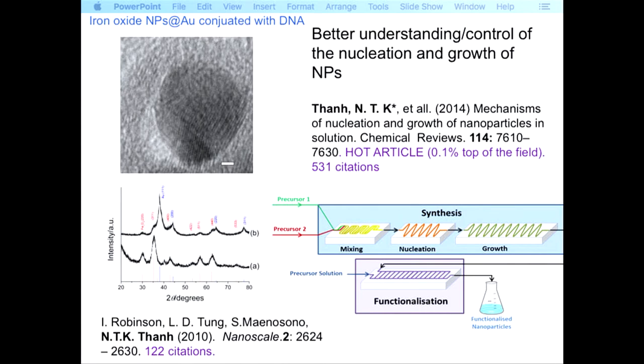Okay, you can see here that I can give you all the ingredients and everything else, and you're going to repeat the experiment. It might not really come out the red, ruby, beautiful color. It might aggregate, okay? So there is a lot of things to control. So now if you use a microfluidic, you can control the flow rate, the addition, the order of the addition, the residence time, and the mixing time, so then you can have more control of the synthesis of nanoparticles. So you have a more robust system and also the scaling up.